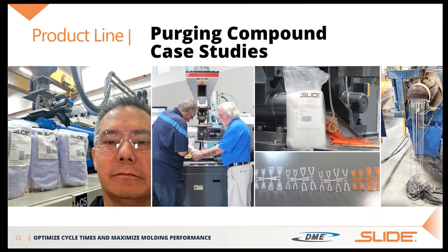I went in there with the Econo Purge, and with a 15-minute soak and 7 shots, we had them up and going. So in 20 minutes, we had them going, black to clear with no problems. They ordered a Gaylord on the spot. That was a real good example of how thorough, how quick, and how good our purging compound works.